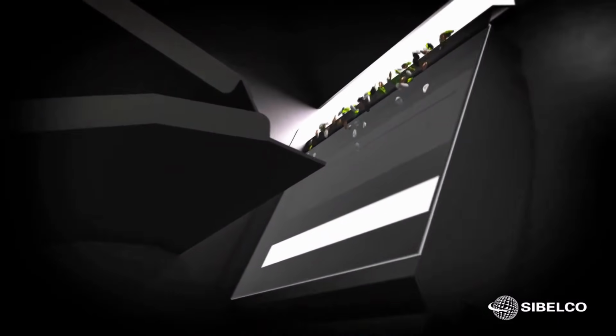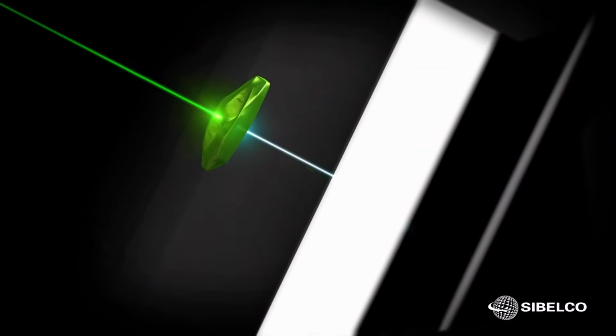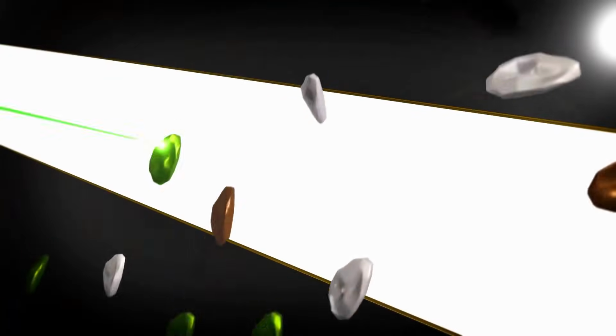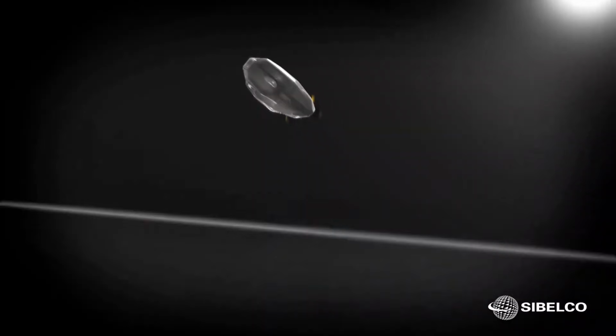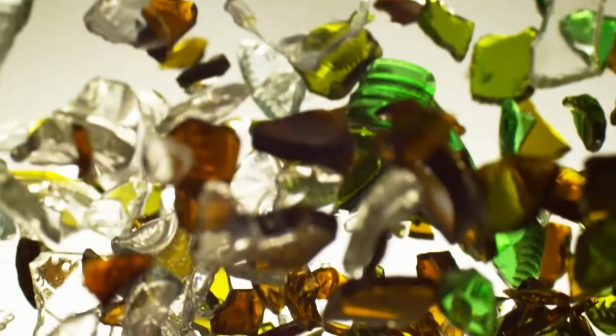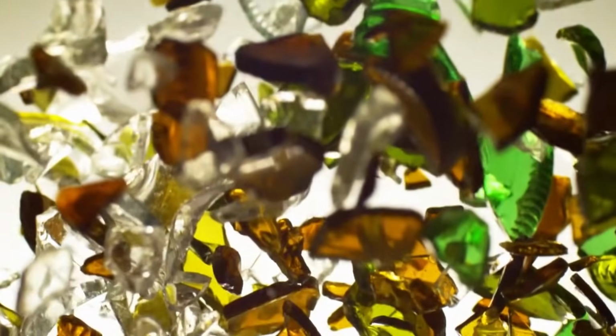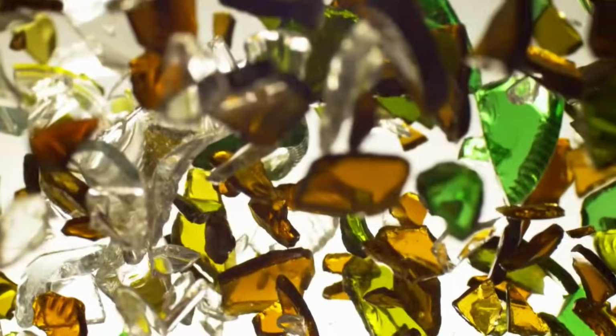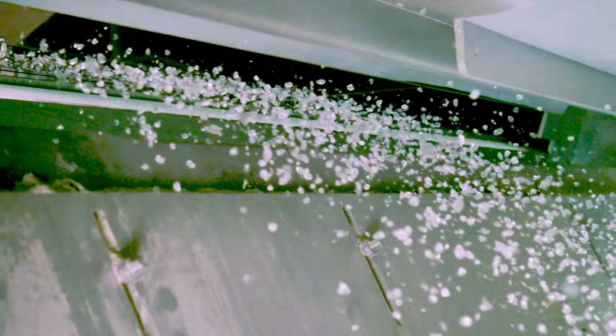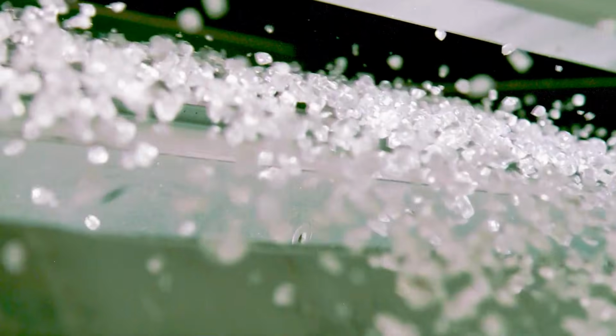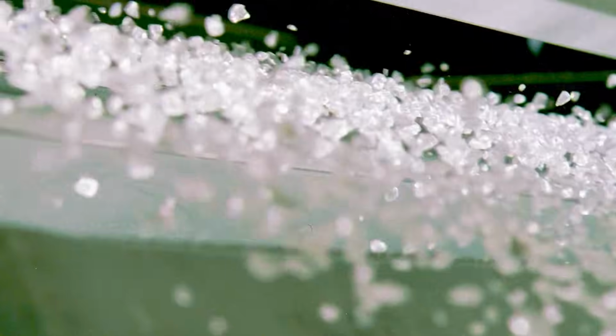This is the most technologically advanced stage of the entire process. As cullet cascades through the sorting system, laser sensors continuously scan each fragment, analyzing color, wavelength, chemical composition, size, and shape. When the system identifies a piece that doesn't belong, whether it's the wrong color glass or a ceramic contaminant, it fires a precisely timed burst of compressed air, diverting that piece into a separate stream. The reaction time is measured in milliseconds, with pneumatic valves responding faster than the blink of an eye.